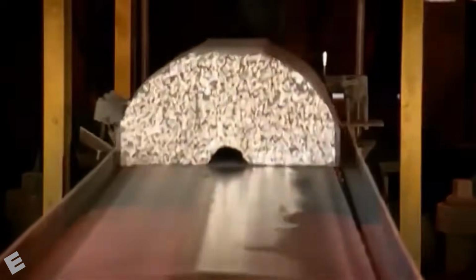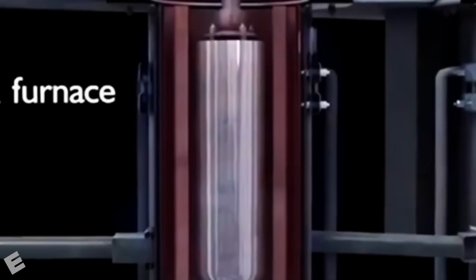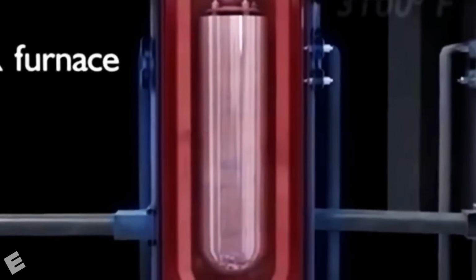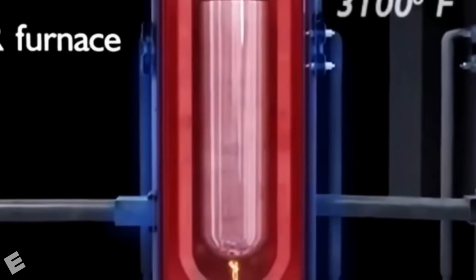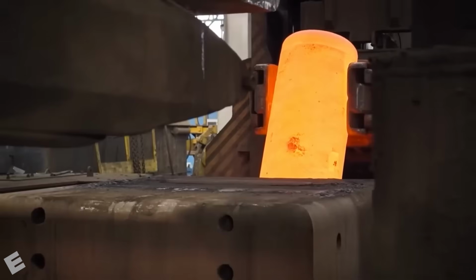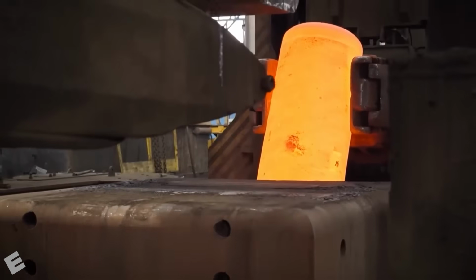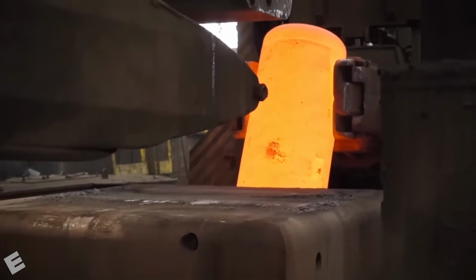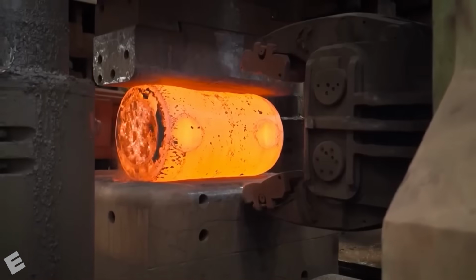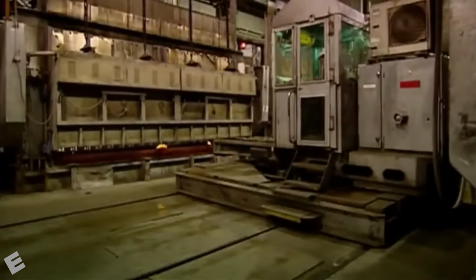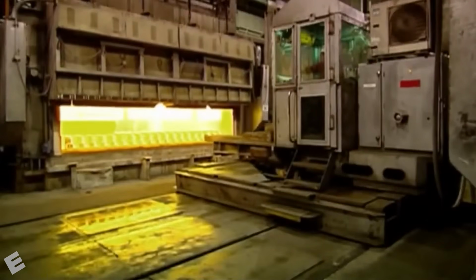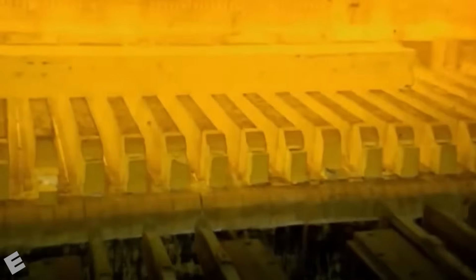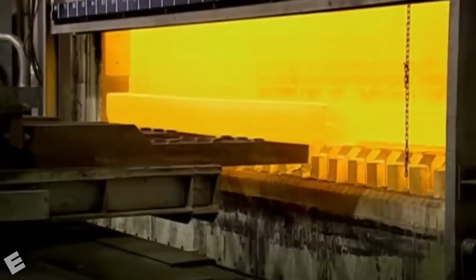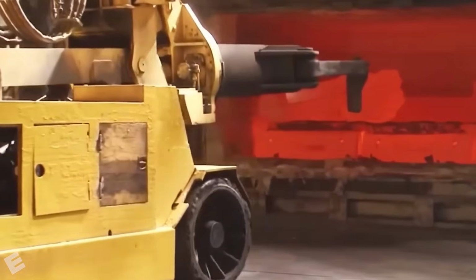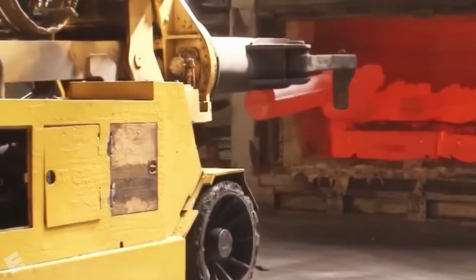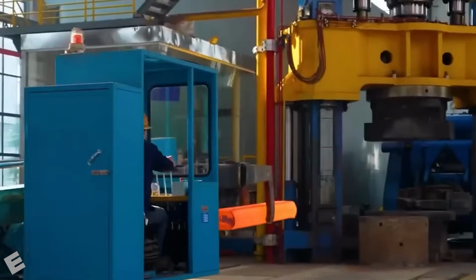These blocks are then melted inside a vacuum arc furnace. Powerful electric currents generate an arc that produces enough heat to melt the titanium. The vacuum prevents the hot metal from reacting with oxygen and other gases. After melting and solidifying, the material forms massive titanium ingots. In many cases, the titanium is melted more than once to improve its purity and ensure that its chemical composition is consistent throughout the entire ingot. Once the ingots are complete, the next stage begins, transforming these enormous blocks of metal into useful industrial shapes.